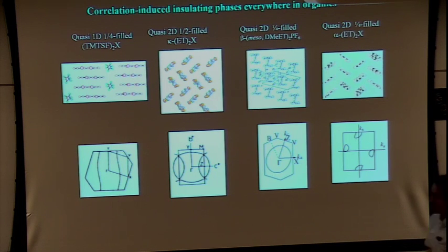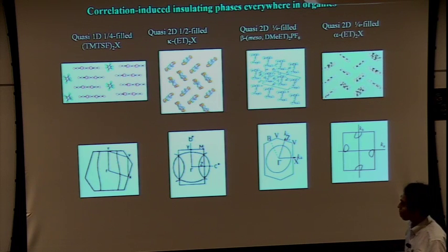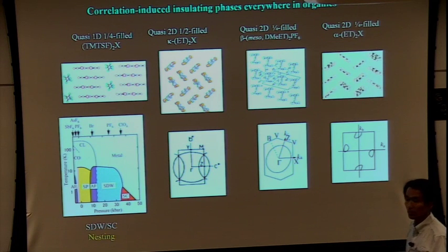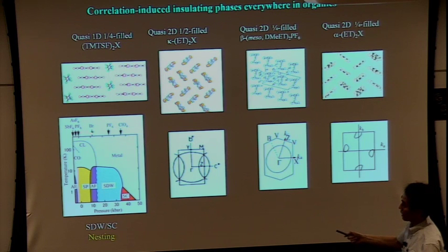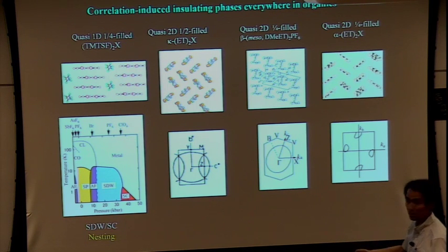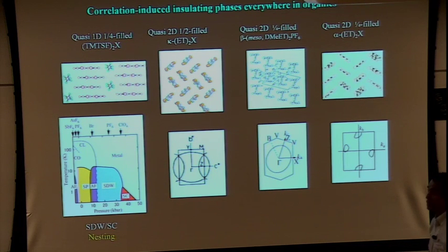However, in reality, the ground state is not metallic for any of these materials. And this is at pressure, okay - at ambient pressure, for example, this material undergoes a spin density wave transition. If X is bromine, there's antiferromagnetic order; if X is PF6, the spin Peierls state is the ground state. But if you apply pressure, the metal emerges, and at low temperature, superconductivity appears.